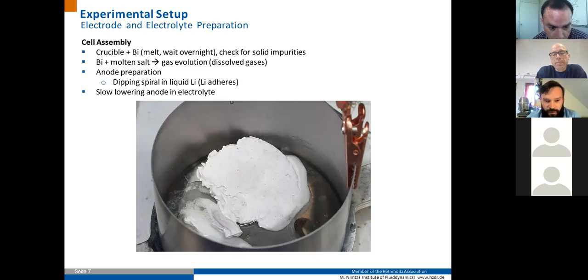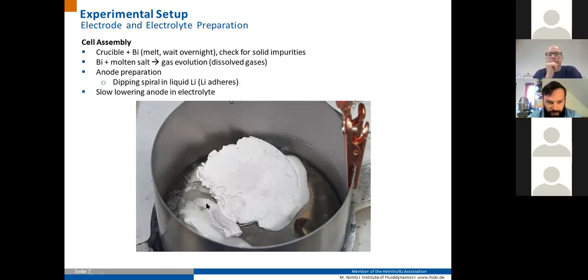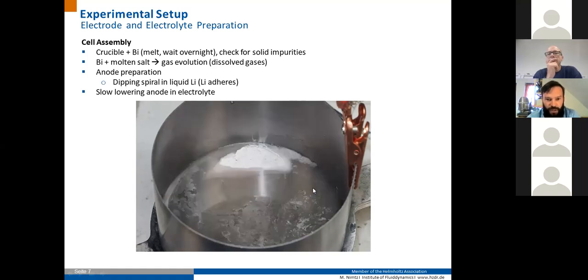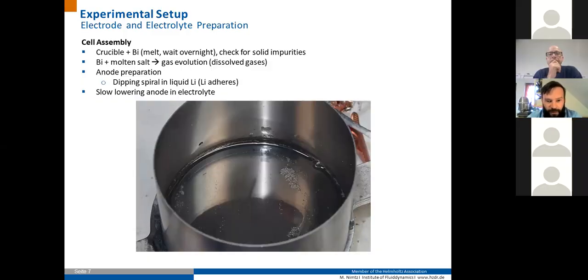If the bismuth is fully molten and impurities are gone, the salt mixture is added. Here this is quite at the beginning. It starts to melt here, and there's a big solid chunk of salt mixture, which then melts over time. Then there's another waiting step to wait for dissolved gases in the salt to get to the surface and hopefully to leave the salt mixture. You can see here there are lots of small gas bubbles, which can be quite hard to remove from the salt mixture because they stick to the salt surface, also to the bismuth layer surface, and to the crucible, and it takes lots of time to be able to remove these gases completely.